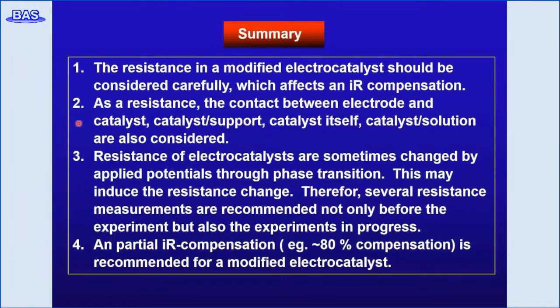The resistance of electrocatalysts was sometimes changed by applied potentials through phase transitions. This may induce resistance change. Therefore, several resistance measurements are recommended not only before the experiment, but also while the experiment is in progress. Partial IR compensation, therefore, is recommended for a modified electrocatalyst.